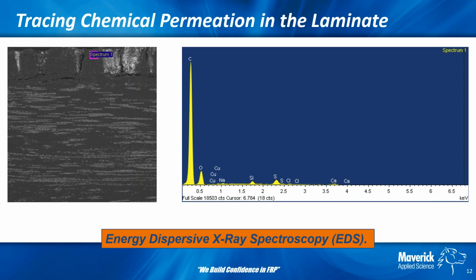So energy dispersive X-ray spectroscopy, EDS. This is another one of our tools that we can use in an examination of destructive testing. What you see here, if you look at the left part of the slide, is spectrum 1. This is basically a sampling we took at this location. As you can see, the crevices in the surface of the veil here. So we're right near the surface of the corrosion barrier.